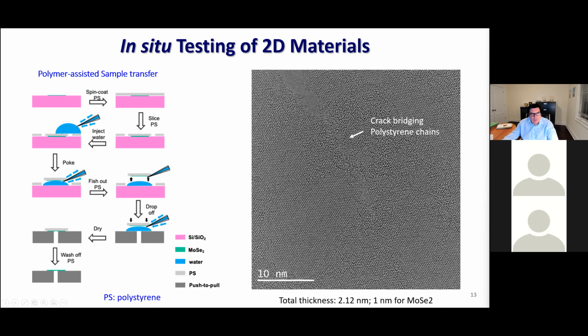And interestingly, and we studied this before on graphene oxide with polymers, this polymer has a nice toughening effect. And so what I will show you next is the measurement of the toughness of this material but now it's a composite, it's a laminated composite, if you wish, extremely thin, total thickness on the order of 2 nanometers with 1 nanometer the 2D material and then the polymer.